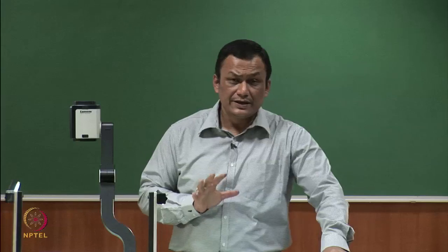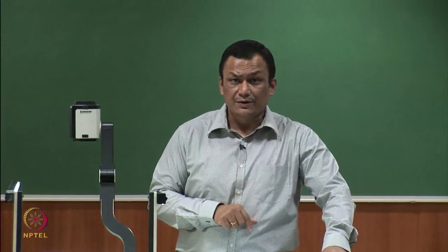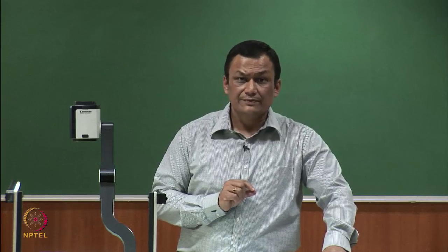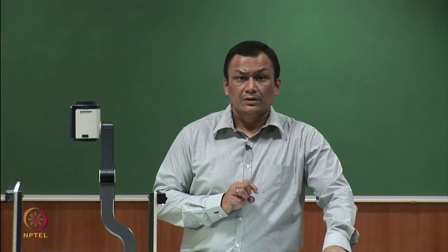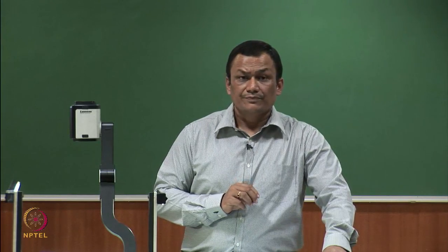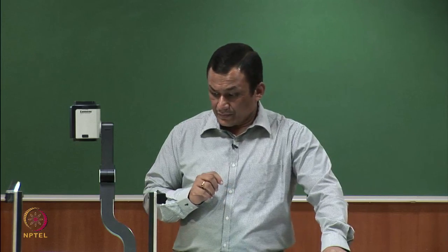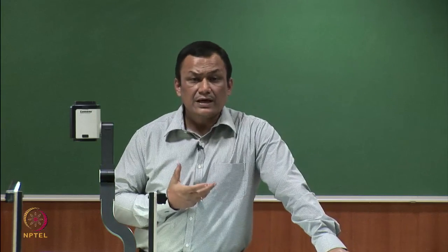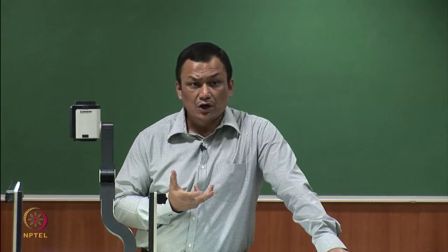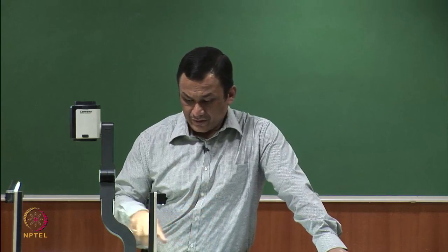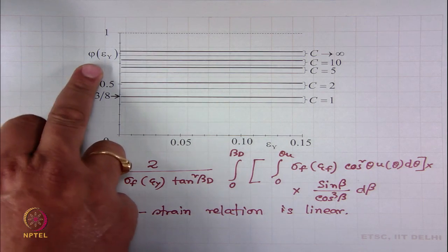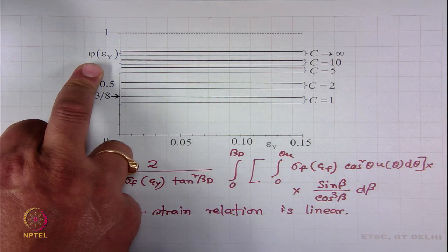So, what we learn here with this theoretical example, we learn that depending on the anisotropic character of fibers in yarn, the numerical value for coefficient of utilization will change.